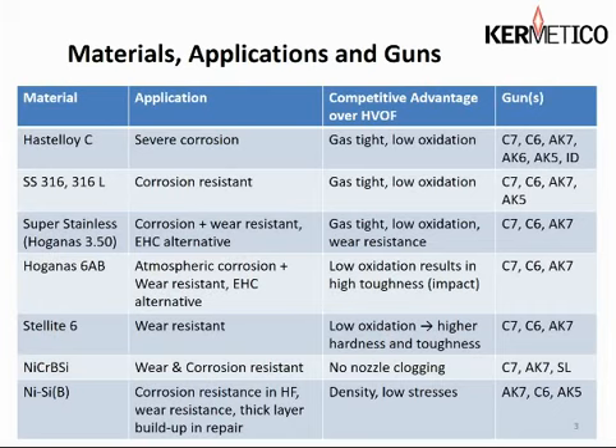Nickel chrome boron silicon is a wear and corrosion resistant coating. We get no nozzle clogging with it, and we spray that with our larger AK-7 gun and our low melting point material guns.